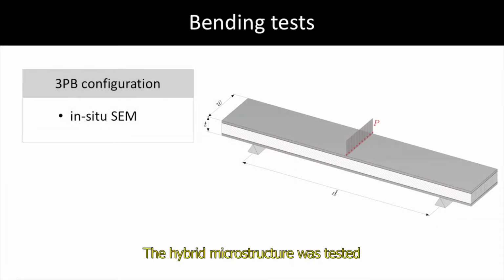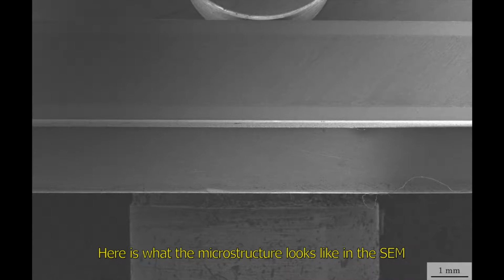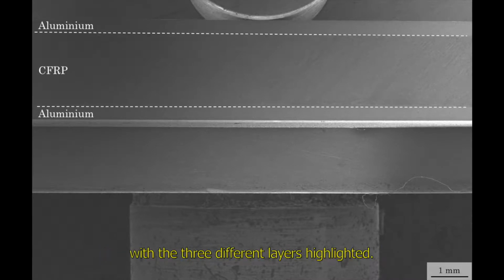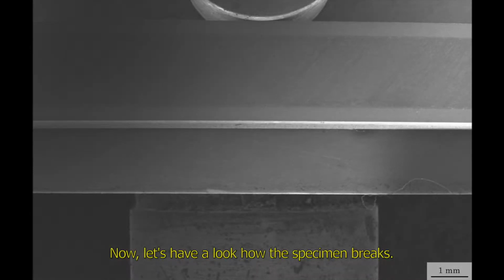The hybrid microstructure was tested in 3-point bending in an SEM environment, just like the cross-lamellar CFRP. Here is what the microstructure looks like in the SEM, with the 3 different layers highlighted. Now let's have a look how the specimen breaks.